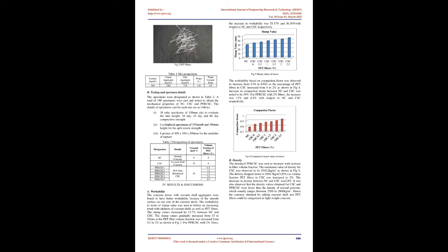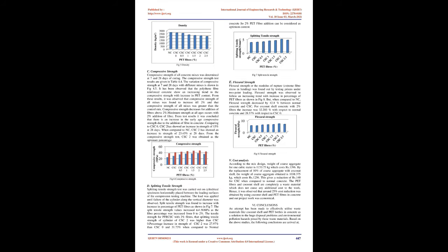Polyethylene terephthalate, PET, fibers having an aspect ratio of 88 were cut from waste PET bottles, Fig. 2. The length of the fibers was 40 mm. Potable water available in the laboratory, which satisfies drinking standards, was used for the concrete mixing and its subsequent curing. The mix proportion used is as given in Table 1. The increase in workability was 55.17% and 36.36% with respect to NC and CSC respectively.